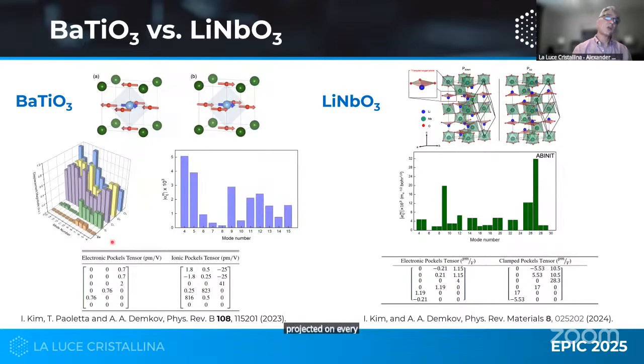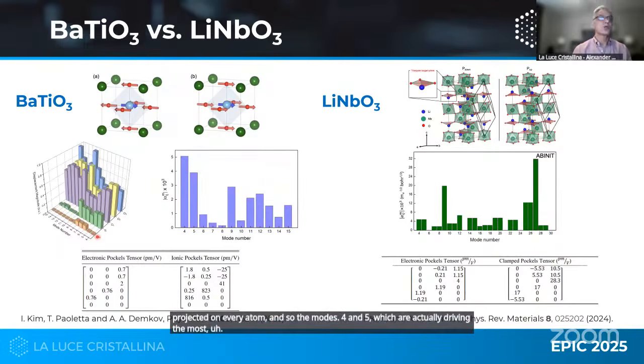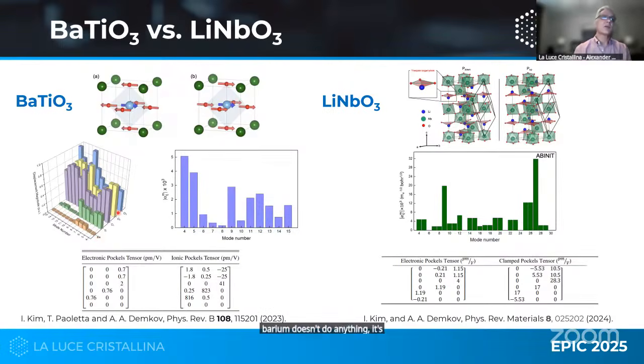And so the modes 4 and 5, which are actually driving the largest portion of the Pockels effect, barium doesn't do anything. It's a movement of titanium and oxygen like here. And that's the contribution. This is ionic susceptibility. What it amounts to, if you look at how each effect of this red, green, and blue contributes to the